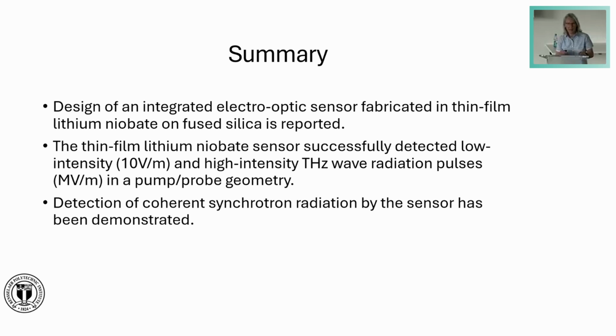Okay, so I'm towards the end of my talk. We designed and fabricated an integrated electro-optic electron beam sensor in thin film lithium niobate. We have now successfully tested the sensor, detecting in a pump probe geometry electric fields of low strength and of high strength. And we have also approached electron beam diagnostics by detecting coherent synchrotron radiation, which requires the step of synchronizing the probe laser with the terahertz signal.